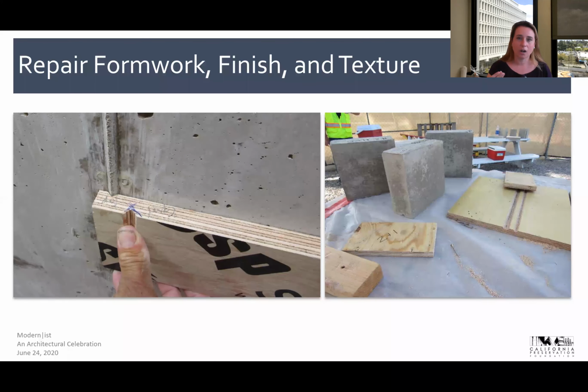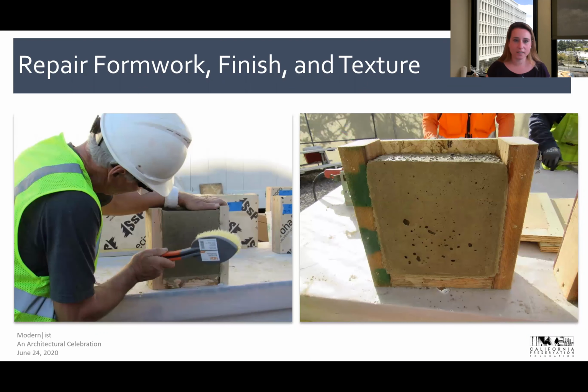There's a little sheen on the Salk Institute, so we needed to get that sheen and that smooth form face, but also we had to have formwork that, with the concrete mix, would allow us to achieve bug holes. And again, those bug holes were probably one of the most challenging aspects of the development of the repair process on this. But ultimately, we did come up with a procedure, again tweaking the mix design slightly, the placement techniques, the consolidation techniques, but also the craftsmen doing the work came up with a very technical solution: once they remove the formwork, tapping the surface with a nylon bristle brush.